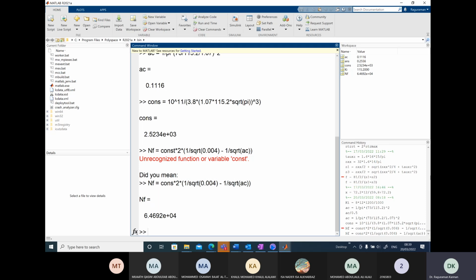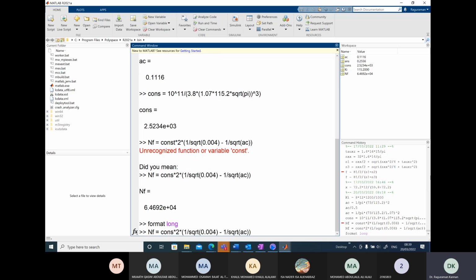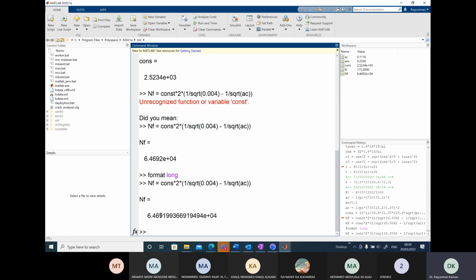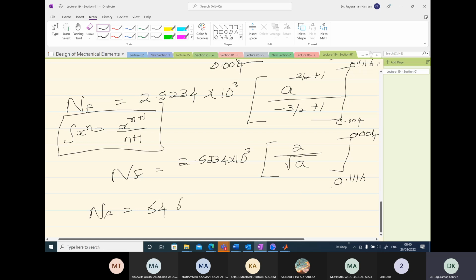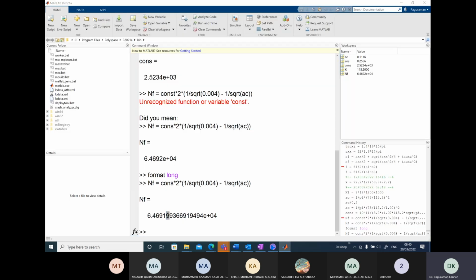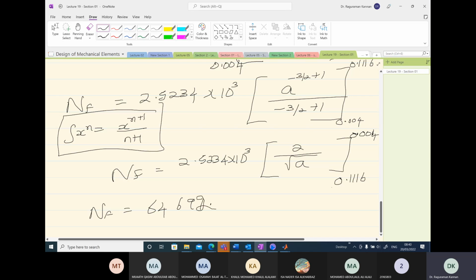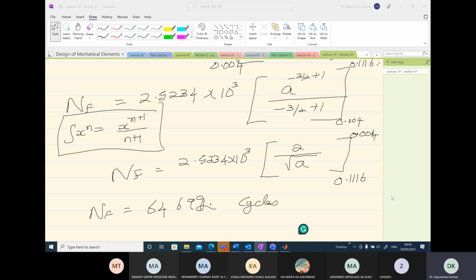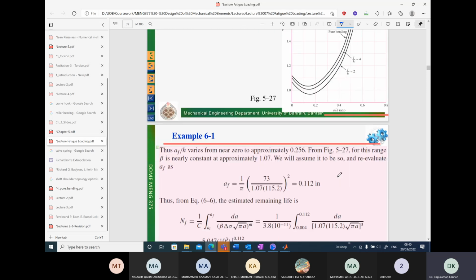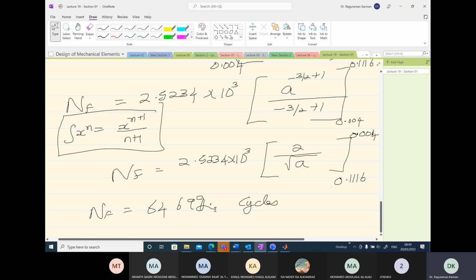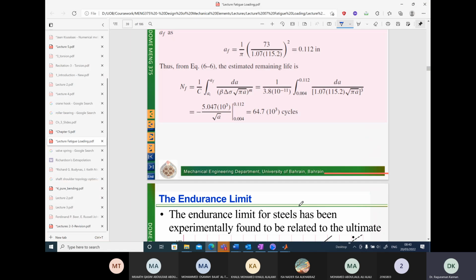Okay, we get 64692, whatever is the number of cycles to failure here. So 4 digits, 1 2 3 4, so 64,691 cycles, so 0.99. Number of cycles to failure is this much, 64,000 some cycles. So let's see what is the value they have calculated. Similar, 64.7, so thousands, around 7,000 cycles. Okay. So this is how we find the life of the specimen based upon the linear elastic fracture mechanics calculations.